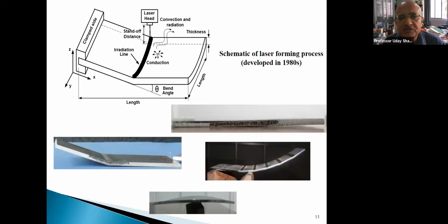Now, these are the traditional metal forming processes, but there are also emerging, somewhat non-traditional metal forming processes. Here at IIT Guwahati also we have done such experiments, where we are deforming the material only by heating through a laser. And even the thickness, you see that its thickness is very large. But if I do it by mechanical bending, there are chances of cracks here on the back side, but here there is no crack.